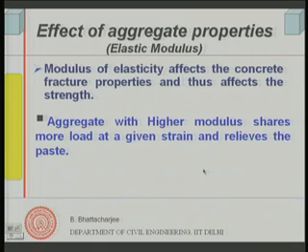Aggregate with higher modulus shares more load at a given strain and relieves the paste. The whole idea is, when I have loaded a concrete specimen, since the aggregates and paste are bonded, there is a bond existing between the two, they will be undergoing the same deformation at their interface. In other words, they will be under the same strain.